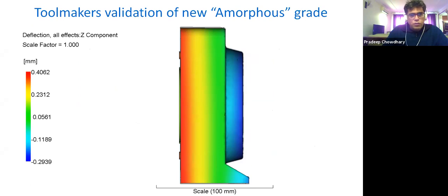Fantastic because even though we have a warpage in the assembly direction of about 0.4, it's extremely uniform if you see along the edges. So it sort of neutralizes in terms of within tolerances. The net effect of warpage that we saw was just barely about 100 microns, which was extremely comfortable for the fasteners to assemble flawlessly.